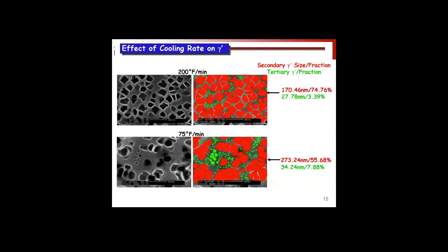But you can see here we've got roughly 78% gamma prime fraction, with roughly 170 nanometer size particles for the secondary gamma prime, and the tertiary here about 4%. If we slow the cooling rate, we get a higher fraction of tertiary, a lower fraction of secondary, and the secondary gamma prime particles are significantly larger. Now you can probably begin to see why the creep properties are so good.